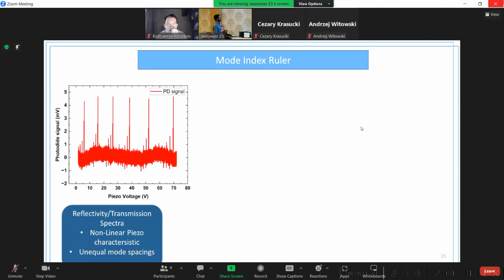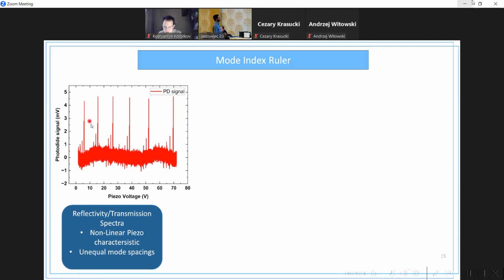In a typical experiment, this is what the spectra looks like. You change the piezo voltage, and you record the signal on the photodiode. As you can see, if you were tuning the cavity length, you would expect that these sharp resonances would appear at constant cavity length difference.